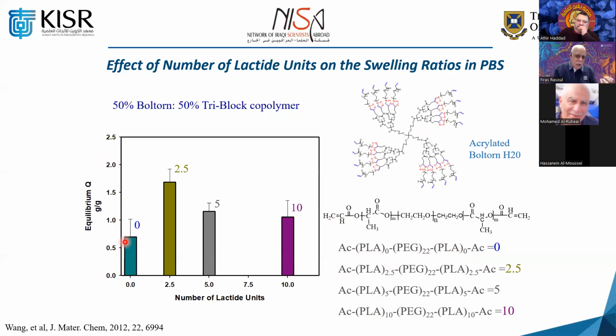Swelling is relatively good, okay? But when you start increasing the lactic acid, because of the phase separation, because of the porosity, it starts to take more water. And if you go to 5 repeated units, you find the swelling rate starts to reduce. And the reason why it is reducing is because you're introducing a hydrophobic component, which is the polylactic acid. And if you go to 10 repeated units, you see they are almost quite similar. So there is no change. So we thought probably this is the right composition. We should really focus our study on the 5 repeated units on both ends, which is tri-block PLA-PEG. Use it with this Boltorn H20 functionalized with acrylate.